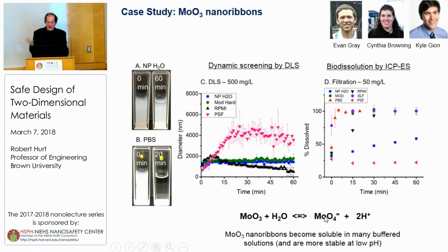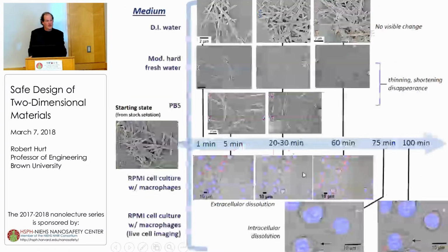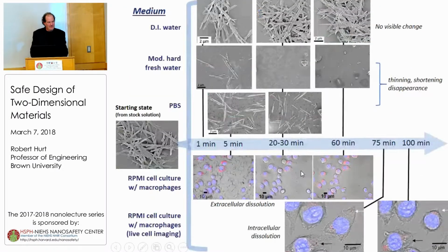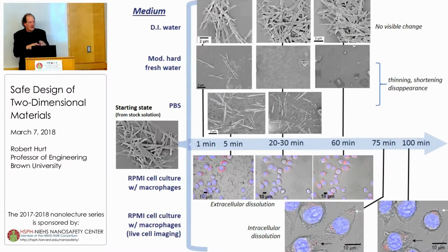And so our combination in our field of dilution plus the use of buffers renders a lot of these materials quite soluble that would be listed normally as poorly soluble or insoluble. And that's the case with molybdenum trioxide. It's asbestos-like, but it dissolves over some time frame. But it's about the same time frame as required for cell uptake. So whether or not it can have a fiber-like effect on cells is still of interest.